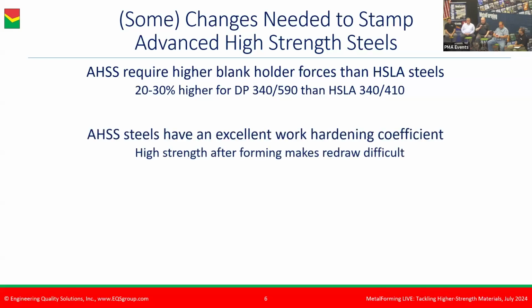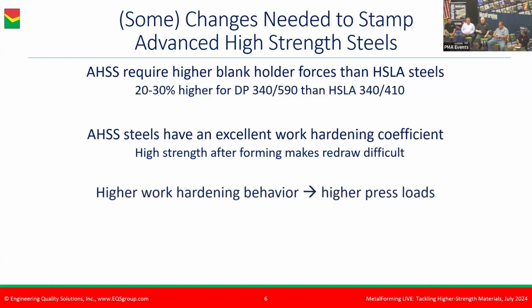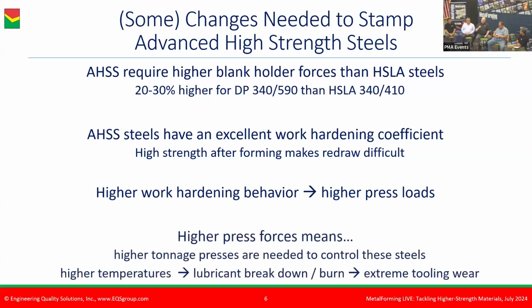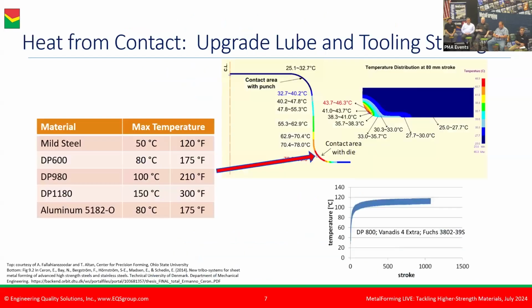One of the characteristics of all of these advanced high-strength steels is that they work harden to a very strong degree, literally and figuratively. What that means is that as you're forming these higher strength products, they become even stronger. And that's going to have certain implications, because if you're dealing with a higher strength product that becomes even stronger when you're forming it, you're going to generate increased press loads, which means that your press has to have the necessary tonnage capability. But you'll also see that there's going to be additional temperature, even though you're only doing room temperature stamping. These forming processes will increase in temperature, and that's going to lead to the potential for lubricant burn-off. That's going to increase the amount of tool wear.